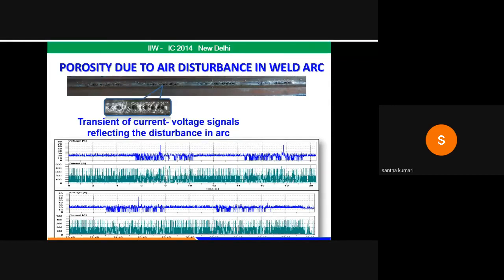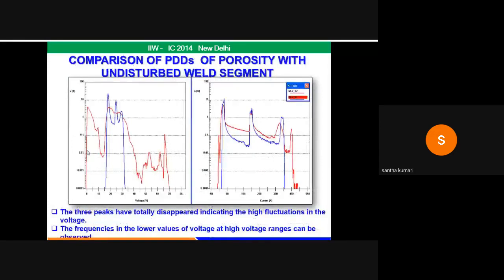The transient of the segment with pores is shown below, and here is the PDD of the weld without defect and the signature obtained with porosity. This comprises some undisturbed portion also. So the volatility as well as the characteristics of the stability of the three clear peaks are disturbed or reflected in the PDDs.